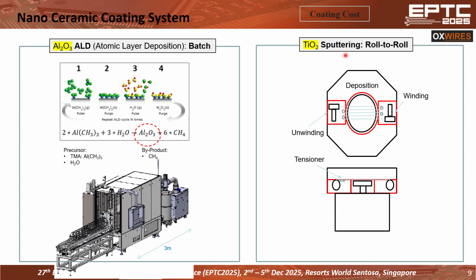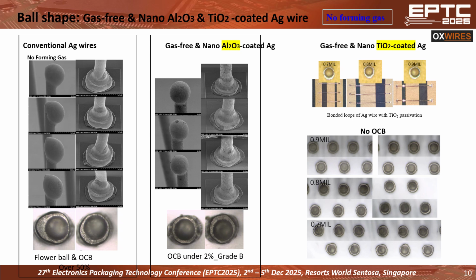The biggest difference between the two coating systems is that sputtering uses a roll-to-roll method, such that the wire is in motion during a deposition operation. On the other hand, ALD makes use of the batch type, meaning that a wire does not move during a deposition operation. As of now, sputtering is more expensive than ALD, and we want to diversify the coating cost options as well. And now I'm going to show you a lot of experimental data.